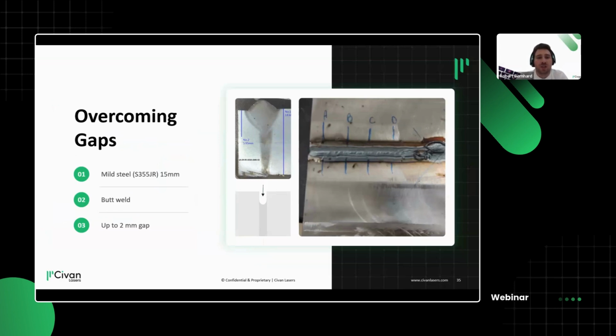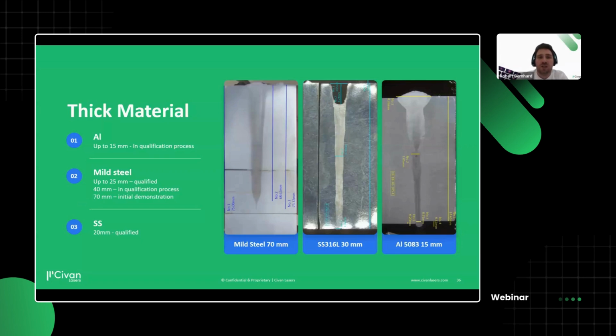Usually we are able to get very deep penetration of butt welding. You can see it here, 15 millimeters of aluminum, 30 millimeters of stainless steel, up to 70 millimeters. Now we're talking 100 kilowatt laser power territory, but this is something where you can do these things in a single weld compared to manual labor, like doing weld after weld and inputting a lot of heat and time. This here, I think, is something where we can do welding even thicker structural steels, mild steels, which also, of course, play a role in automotive stiffness as well.